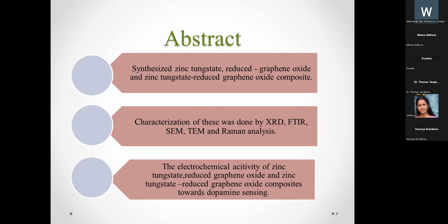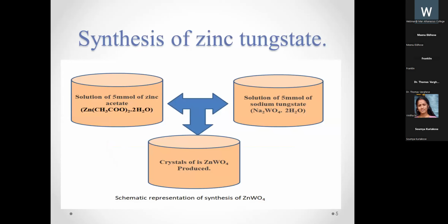Here, I have synthesized zinc tungstate, reduced graphene oxide, and zinc tungstate reduced graphene oxide composites. The corresponding characterization was done using XRD, FTIR, SEM, TEM, and Raman analysis. The electrochemical activity of zinc tungstate and reduced graphene oxide, as well as these composites, was also checked towards dopamine sensing.